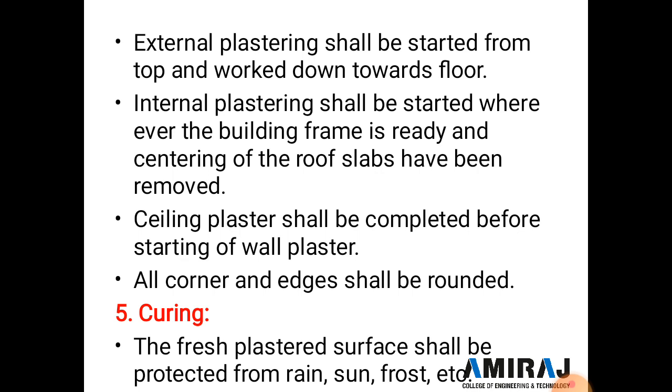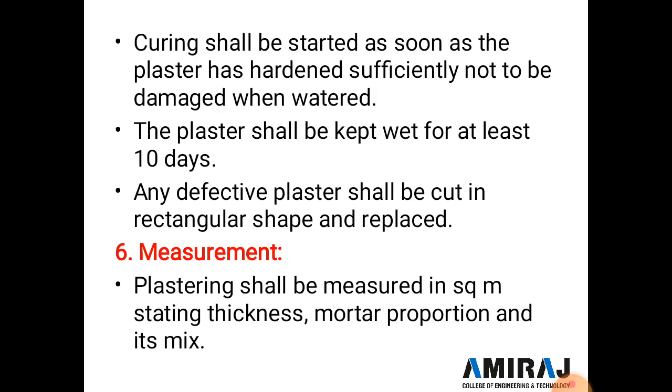The fifth specification is curing. The fresh plaster surface shall be protected from rain, sun, frost, etc. Curing shall be started as soon as the plaster has hardened sufficiently and is not damaged by water, and the plaster shall be kept wet for at least 10 days. Any defective plaster shall be cut in a rectangular shape and replaced with a new one.